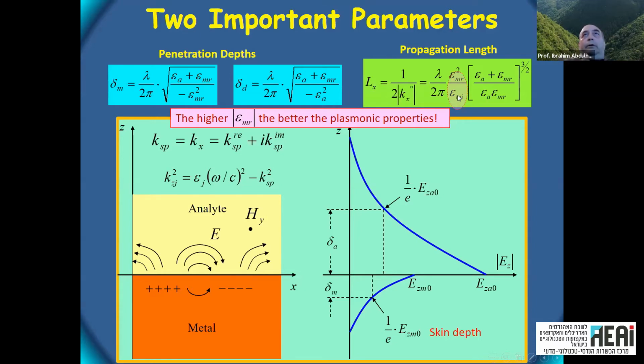As we can see, there is the importance of the ratio between the real and the imaginary part of the dielectric constant of the metal. When it is large, then the propagation is longer. Usually that is better. It gives us higher sensitivity, higher, let's say, figure of merit of the sensor. And even in localized nanoplasmonics, this ratio is very important. It also gives higher enhancement when the ratio is larger. The larger the ratio, the larger the enhancement factor. And we will show some rough approximation. We will show this analytically.